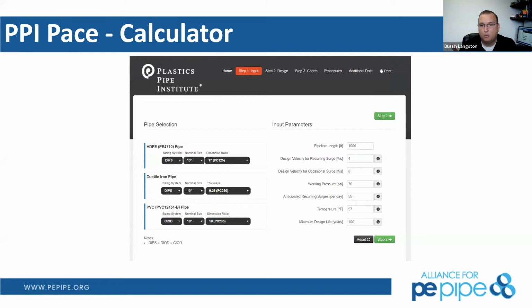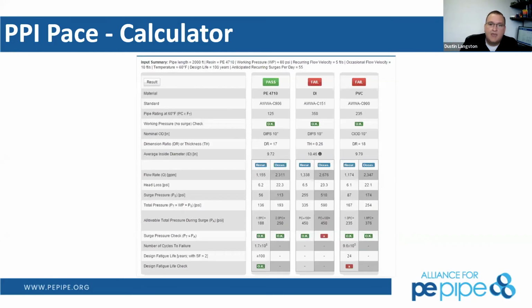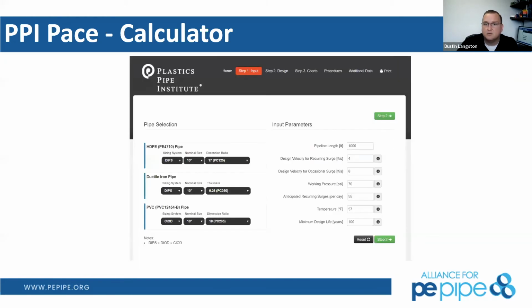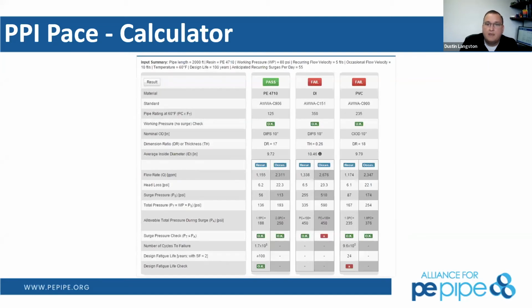Side-by-side comparison, working pressure 70 PSI, temperature 57 degrees, and then we're looking for a 100-year minimum design life. And so it'll actually come through here and give you, hey, what does this look like? Sorry, I also want to mention design velocity here is 4 feet per second, and occasional velocity, so fire situations, things like that, is 8 feet per second. So still pretty conservative. And here we can see PVC failed and ductile iron failed.